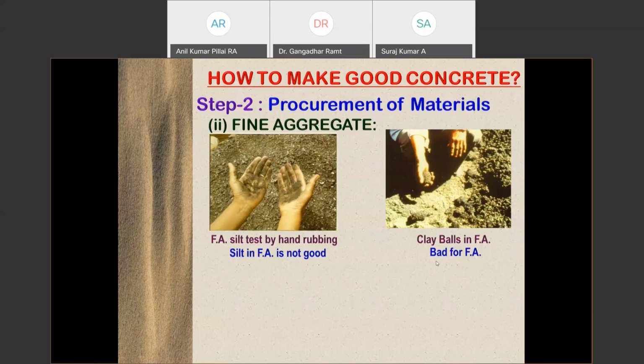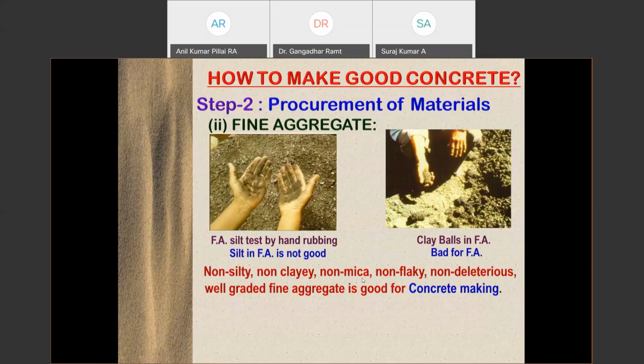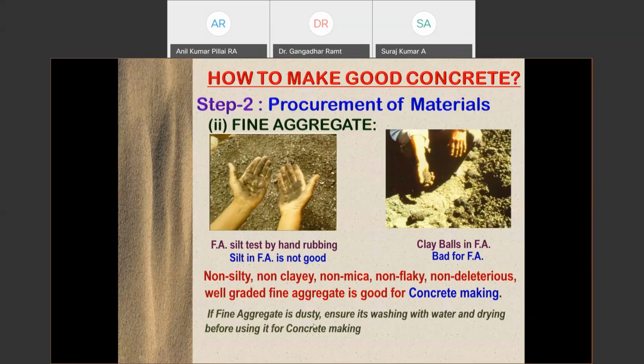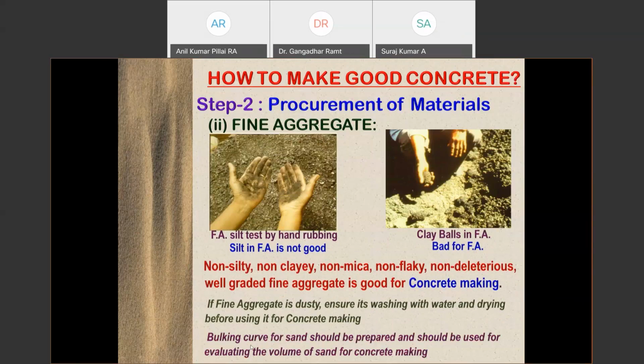So what should we do? What is required is a non-silty, non-flaky, non-mica, non-deleterious, well-graded fine aggregate, which is good for concrete making. Now, if fine aggregate is dusty, we must ensure its washing with water and drying before using it. This is also an important task before us for using aggregate in the field. Bulking curves: because there is a phenomenon of bulking that takes place when it is moist sand, a bulking curve of sand should be prepared and used for evaluating the volume of sand for concrete making. So this is about fine aggregate.